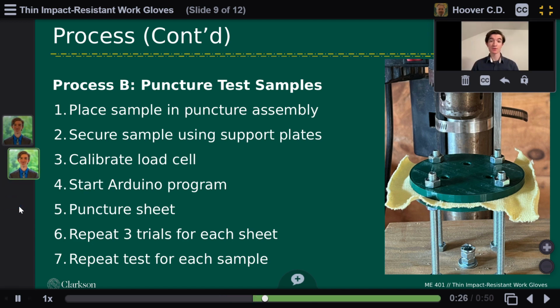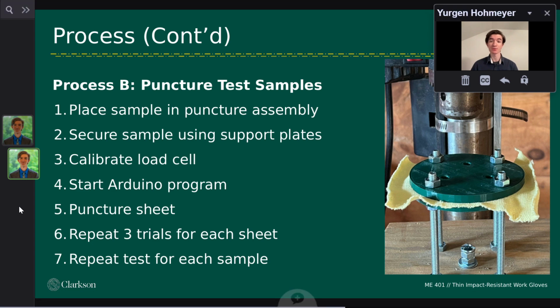The second step in the process was to puncture each set of samples, which was accomplished by placing a sample in the specimen support assembly fixture shown on the right, securing it, and performing the puncture test. However, before each test, as mentioned previously, the CALT load cell was calibrated with a known weight, and the HX711 board gain was set due to the heavy fixture modification between tests.